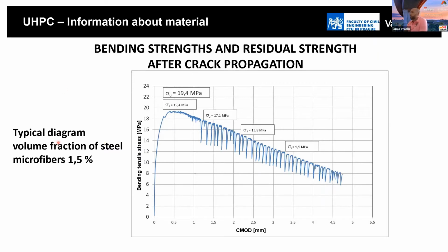We can also see there are three phases of the behavior. The first one is the elastic behavior. That means that if you increase the strain, you will increase the stresses by the same multiplication. In this area, it is the hardening, which is very close to the behavior of steel. After the hardening part, you will reach the maximum value of the bending tensile stress, the bending tensile strength of the concrete. And then there is the effect of softening. But the damage of the concrete is not a damage at a point, and you can see that the material has a great ductility.